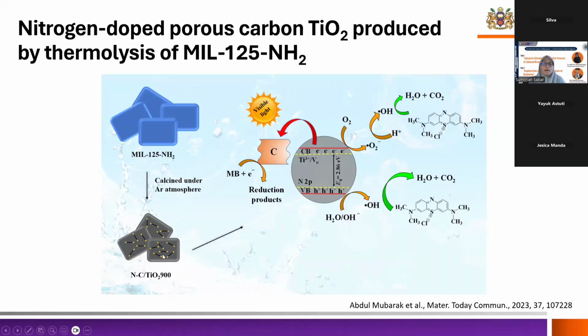So again here, interestingly, because a MOF is a combination between metal cluster and also organic ligand, it was found from our study that this organic ligand has converted into a carbon under calcination. Okay, and because there's a presence of amino group, this amino group contributed to the doping of the nitrogen into the titanium dioxide. So what happened to the mechanism now is that there's an enhanced photocatalytic activity because of the nitrogen doping, where it has decreased the band gap energy of titanium dioxide from 3.2 to 2.86 electron volts.